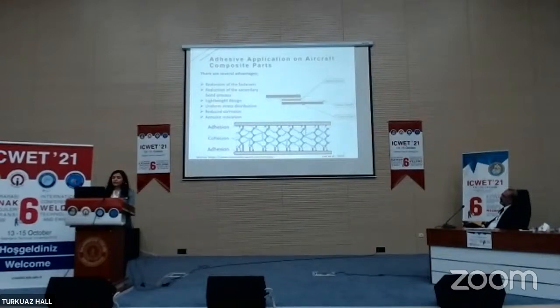The joining method of each component is important for structural materials. Mechanical joining methods such as riveting and bolting are suitable for assembling metal structured components. However, composites are difficult to mechanically join due to their brittleness. The mechanical strength of composites is greatly reduced by fiber breakage and delamination from the machining process. Adhesive bonding is an appropriate method to assemble joints without a machining process. The bonding method has several advantages, such as reduction of the secondary bond process, decreasing the weight of the structures, a uniform stress distribution, corrosion prevention, and acoustic insulation.